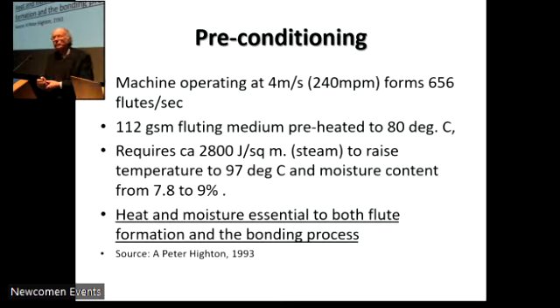So we might have 112 GSM fluting medium preheated to 80 degrees. It requires 2,800 joules per square meter in the form of a steam shower generally to raise the temperature to 97 degrees C, and the moisture content from 7.8 to 9%. And the heat and the moisture control are essential not only to flute formation, to plasticize the medium, but also to the bonding process itself. And these figures were put together by a former colleague of mine from Bowaters, called Peter Highton, in a paper in the American magazine in 1993.